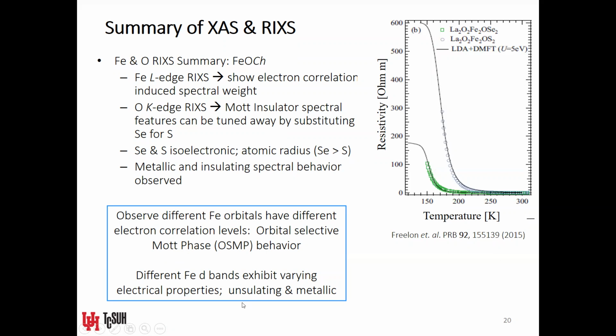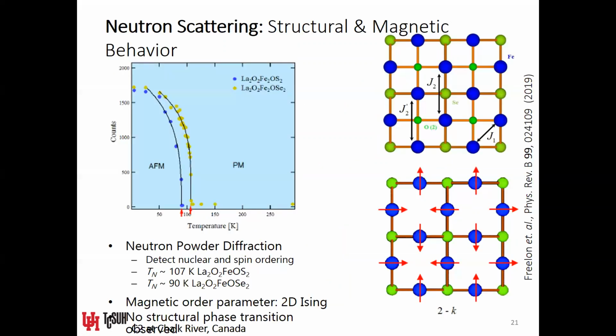The other thing that these data show is that different D bands, through their coupling with the oxygen, actually have more or less itinerant character. So there's some variety in the itinerant character of the D bands. What I want to now do is show some magnetic data that we took on these materials.